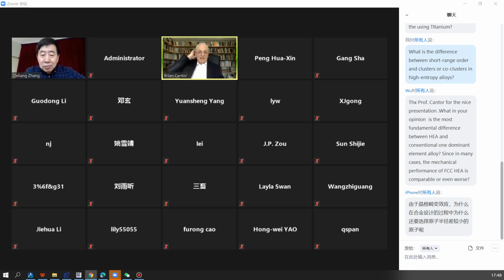And in my review, which is published in Progress in Material Science, it's not actually been fully published. It's in press and it's up on the website. So that's just coming out. And when I looked it up, we have now found by about 3 or 4 different methods, we've been able to get up to between 1 and 1.3 gigapascal yield strengths with still at least 10, maybe even 30 or 40% ductility. That's better than any possible current metal material.